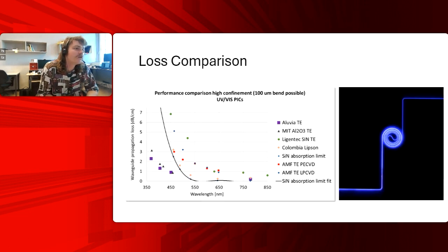If you compare this to other materials, you'll see that black line being the silicon nitride absorption limit, which certain groups have really come close to operating near or even on, and it does show the cutoff that silicon nitride can operate to, just at that 400 nanometer limit. Whereas there are other materials done by MIT with some aluminum oxide, these triangles, just slightly higher than our Alluvia platform. Also, the other materials are done with atomic layer deposition, which is again a little bit harder to integrate into different platforms and is more expensive. Nevertheless, they're also very nice materials, and we can see here that the Alluvia platform can really be at the state of the art when it comes to UV losses in waveguide technology.